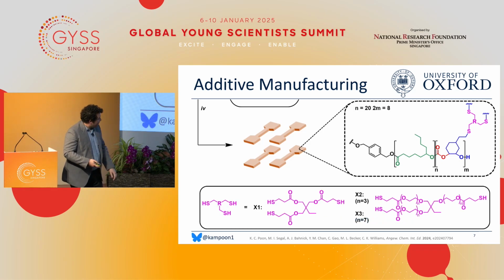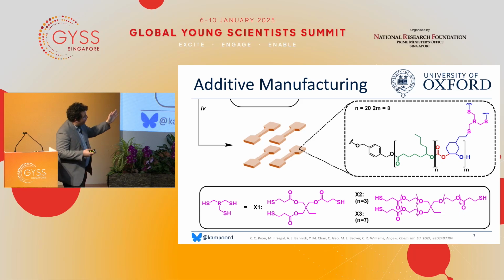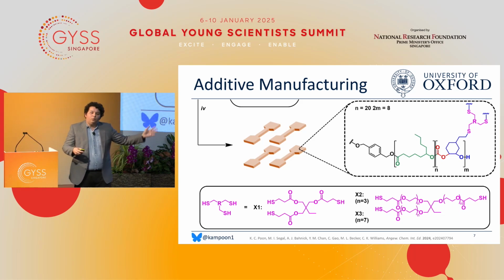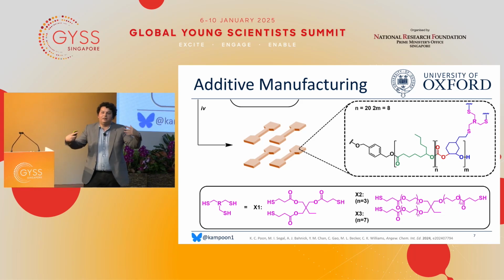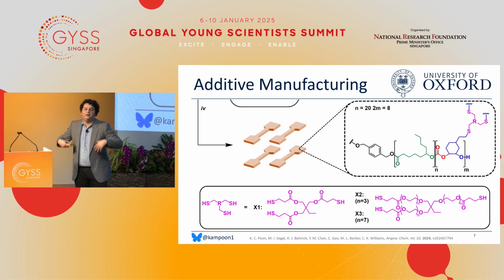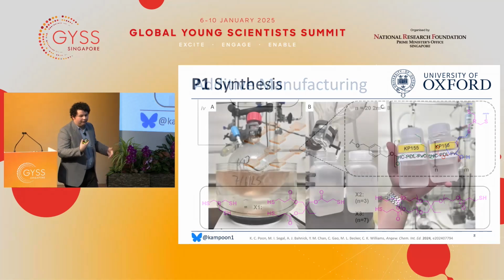Then we can wash up these parts and hopefully have some nice 3D printed shapes with this structure. And specifically, the crosslinkers we were looking at were these three here, which we called X1, X2, and X3. As we go from 1 to 3, we increase the length of polyethylene glycol in the crosslinker. We increase, hopefully, the hydrophilicity of that material.